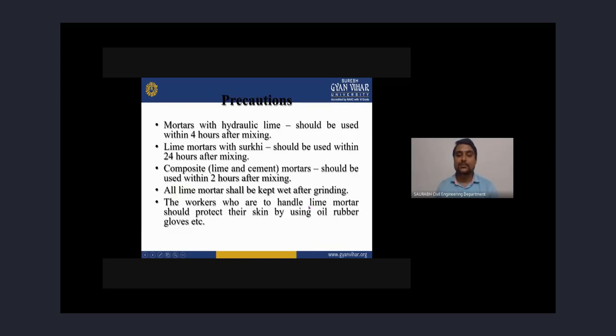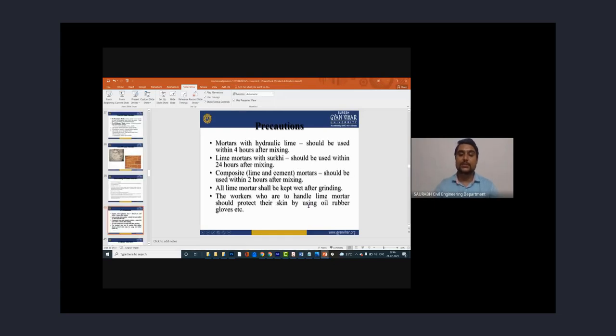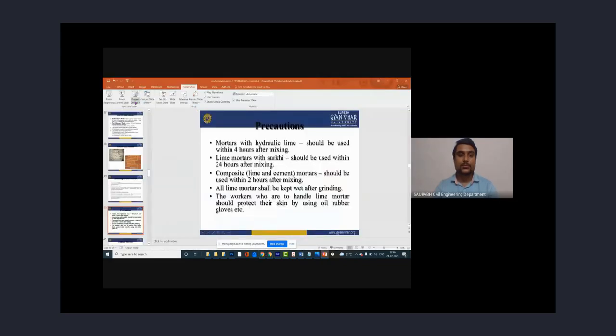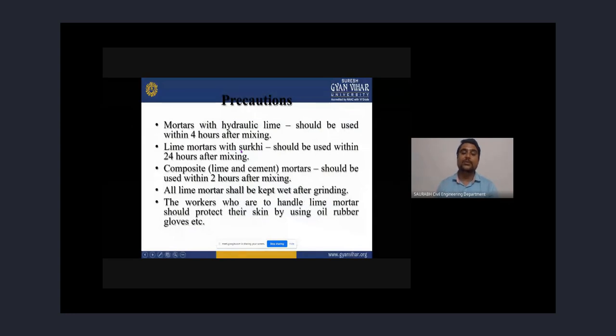Now, what are the precautions we should take care of during the preparation of this kind of mortar? Mortar with hydraulic lime should be used within 4 hours after mixing. Lime mortar with surkhi should be used within 24 hours after mixing, as you can see here. And composite, which is known as lime and cement mortar, should be used within 2 hours after mixing. All lime mortar shall be kept wet after grinding. Workers who handle lime mortar should protect their skin using oil rubber gloves. So there are some precautions we need to take during the preparation of this kind of lime mortar.